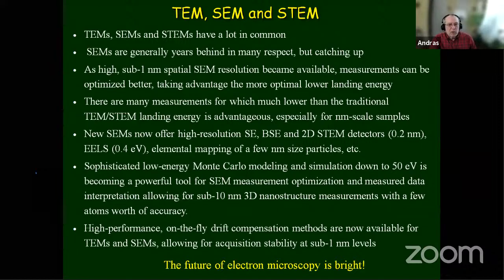At very, very low energy though, under 50 eV, the primary electrons start to behave like any other electrons. That's also a somewhat different realm of modeling that is not developed. So that's one area of improving. High performance on-the-fly drift compensation methods are now available or becoming available for TEMs and SEMs, allowing for stability at sub-nanometer levels, which is critical for many of those results that you've seen already. So as you know, the future of electron microscopy is indeed bright. Next slide, please.